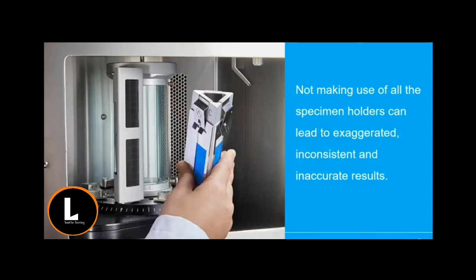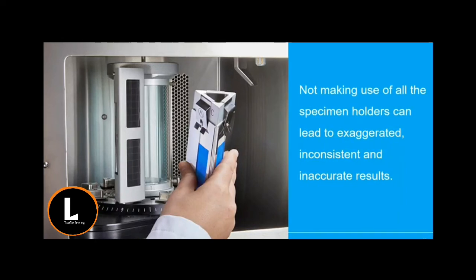The inside of the chamber is thermodynamic. So if you only have one sample, then this will absorb and reflect all of the light and heat, and the air will move differently too. And this can lead to exaggerated or inconsistent and ultimately inaccurate results. If you only need to test one specimen, there is no requirement to waste additional samples. You can put blank mounting cards in, and the black standard thermometer and black panel thermometer are used to take up one of the spaces.